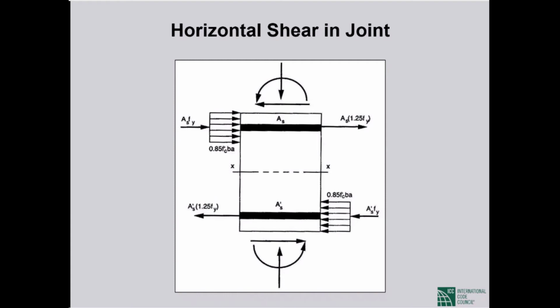The alternatives open to you is you can go for higher concrete strength that would boost shear capacity, but it is square root of f sub c prime. Remember that shear strength is proportional to that, so that makes it ineffective. You increase concrete strength 4 times, 4 to 16 ksi, you get only a shear strength increase by a factor of 2. Or you can go for a larger joint, A sub j, increase A sub j by increasing column size. That is also something the owner wouldn't like.